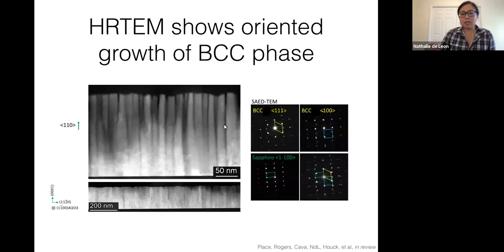The tricky thing about tantalum is that if you try to grow thin films of tantalum, you actually get the very low TC phase of tantalum, which would not be great for a variety of reasons. But fortunately, Dan Prober's group at Yale had figured out in the 90s that you can stabilize the correct bulk phase in thin films by high temperature sputtering. This is now commercially available from foundry services that do sputtering. So what we can do now is grow BCC phase tantalum on top of these nice sapphire substrates.